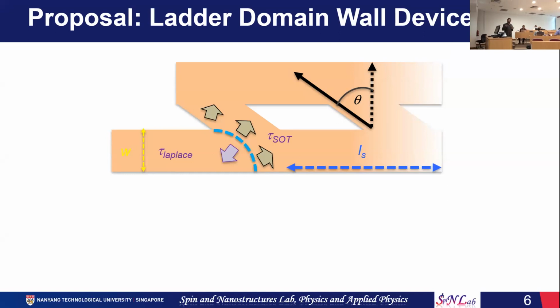I also want to mention the physics behind this device. When the domain wall moves and reaches a particular pinning position, it gets influenced by two torques. One is the spin orbit torque, and the other is the Laplace torque. At this position, the domain wall basically acts as an elastic membrane, just like a soap bubble. Just like surface tension, this torque applies here, and due to the competition of these torques, different kinds of domain-wall dynamics are observed.